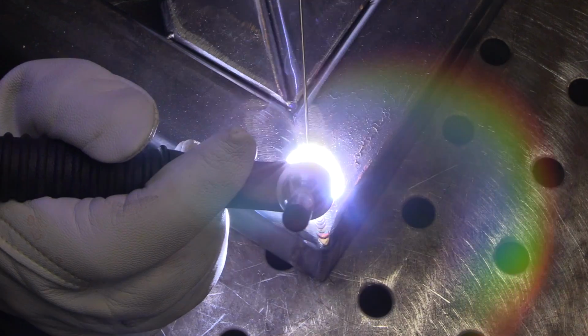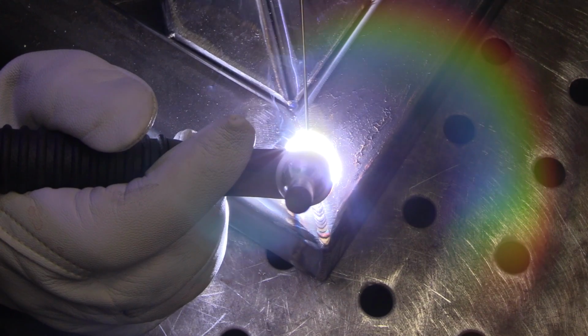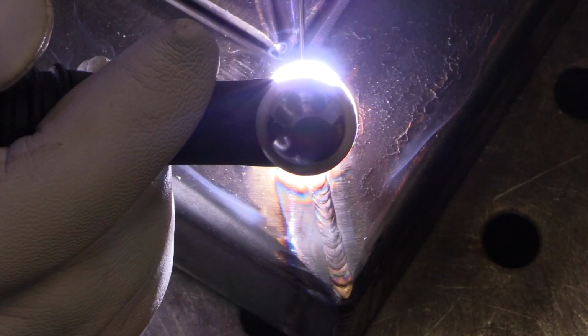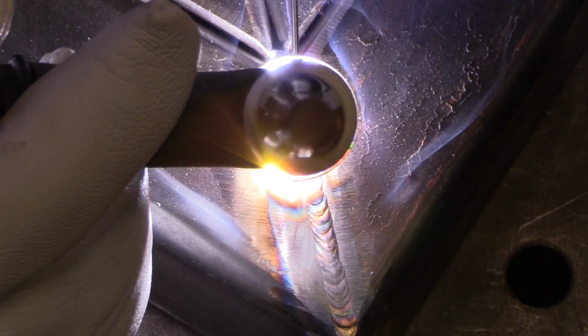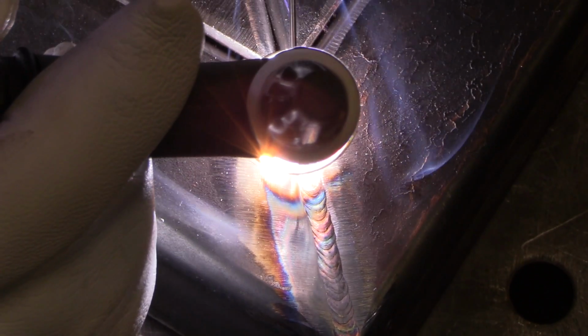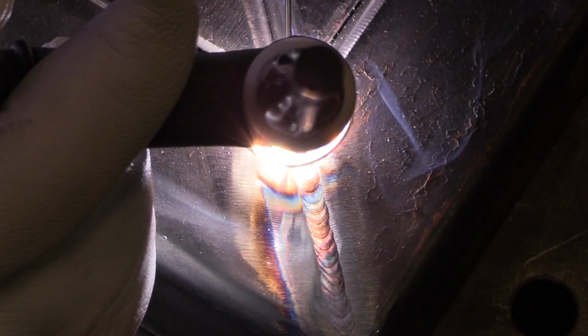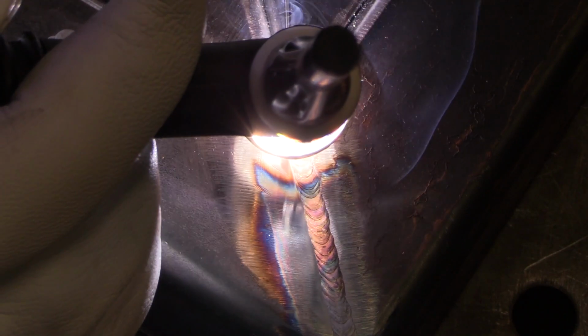But I'm really not trying to get 100% penetration here, because if I do, I'm pulling in oxides from that back side where it's not shielded with argon or anything, and it's going to make the puddle kind of swim around and be squirrely on me, and I don't really want that. So I'm trying to just get some penetration, but not penetrate all the way through. That's my goal here.